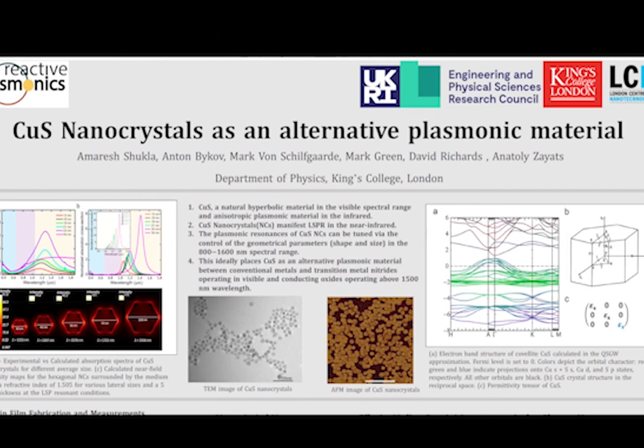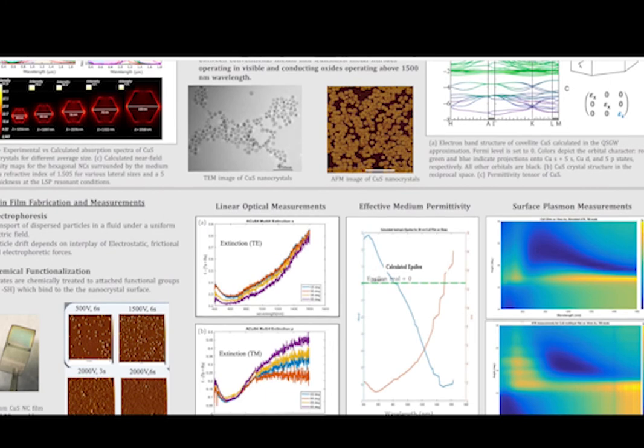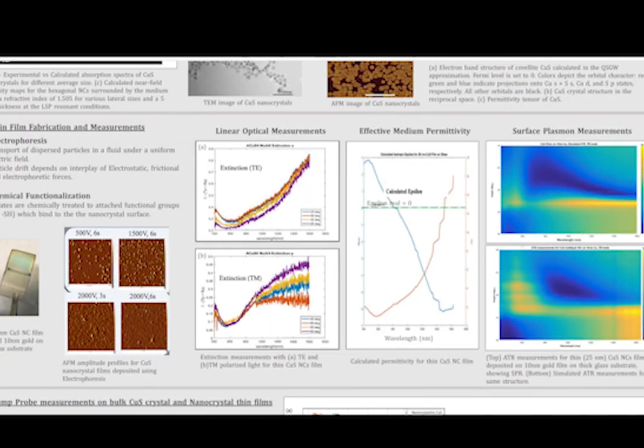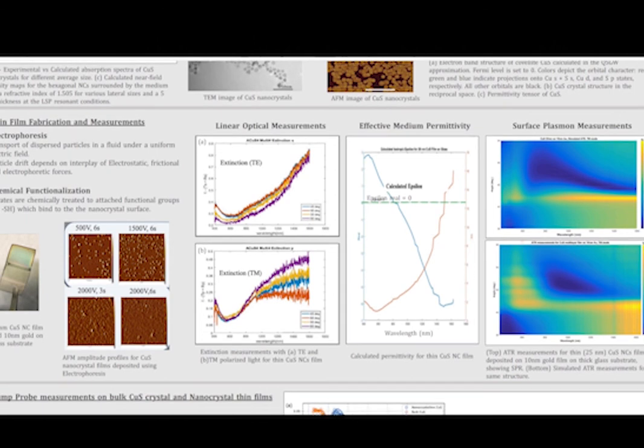This range ideally places copper sulfide in a desirable position, filling the gap between conventional metal and metal nitrides operating in the visible and conductive oxides beyond 1500 nanometers. In this poster, we further demonstrate our study of large-scale thin uniform films of copper sulfide nanocrystals. We use two very different methods of fabrication, one being electrophoretic deposition and the other using chemical functionalization of the substrate to bond with the nanoparticles. Through both these methods, we were able to make smooth, thin films which we then use for various optical characterizations.